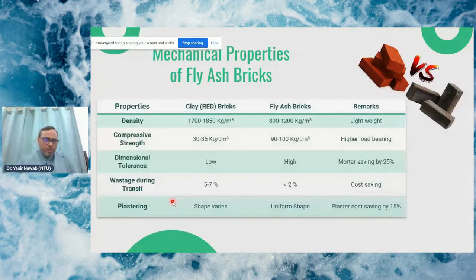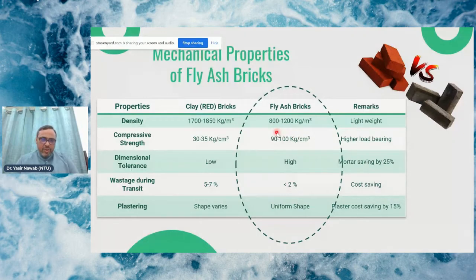If we compare the mechanical properties, the density of fly ash bricks is lesser. They are lighter in weight as compared to the conventional red bricks that we use mainly in this part of the world, in Pakistan, India, Bangladesh. Their compressive strength is good as compared to conventional bricks. Their dimensional tolerance is higher. When we transport bricks, 5 to 7% of them break, and there is wastage. The wastage in case of fly ash bricks is lower, and their shape can be maintained very easily as compared to normal red clay bricks.